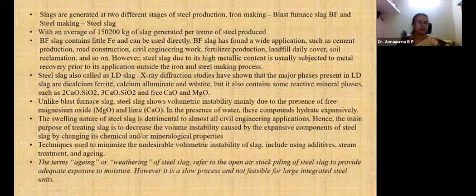The steel slag is also called LD slag, and it contains calcium oxide, silica, calcium, free calcium oxide, and magnesium. These are the reactive minerals present in it. Unlike blast furnace slag, steel slag shows volumetric instability, mainly due to the presence of free magnesium oxide and lime. Because of these two, there is an increase in the volume. In the presence of water, these compounds hydrate expansively. The swelling nature of steel slag is detrimental to almost all civil engineering applications.